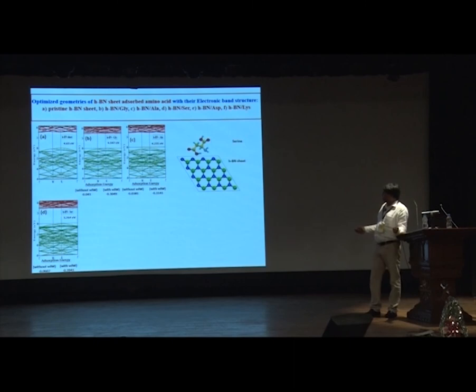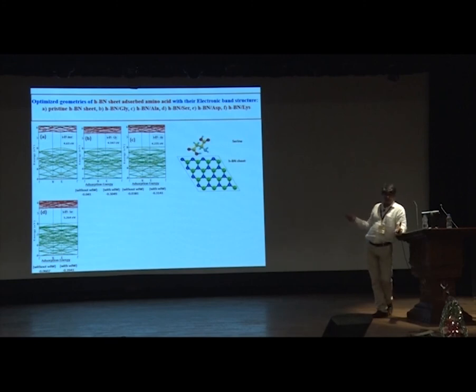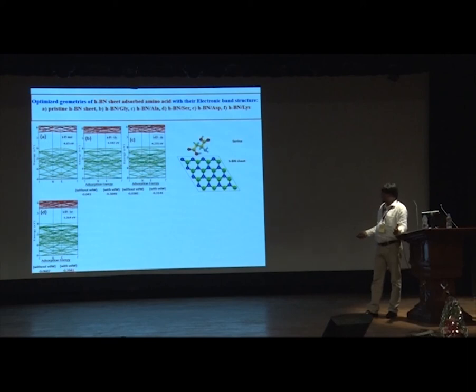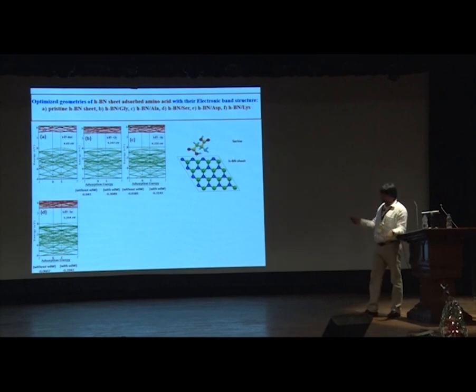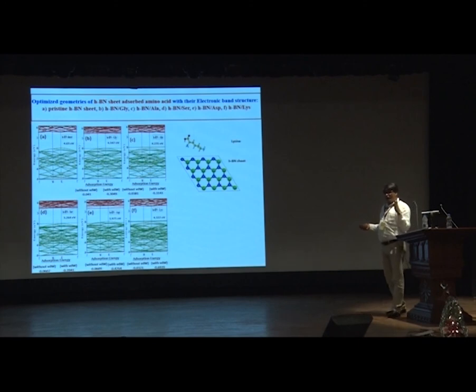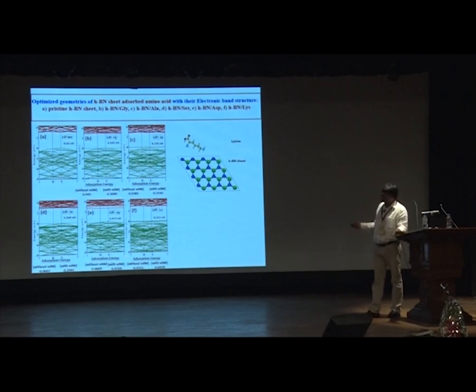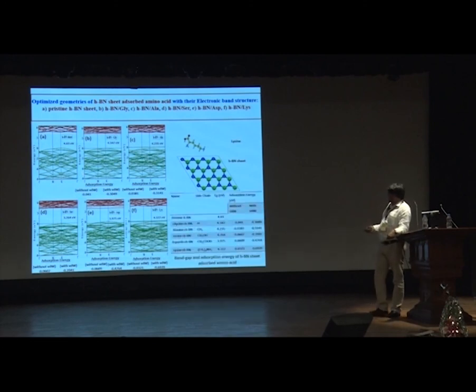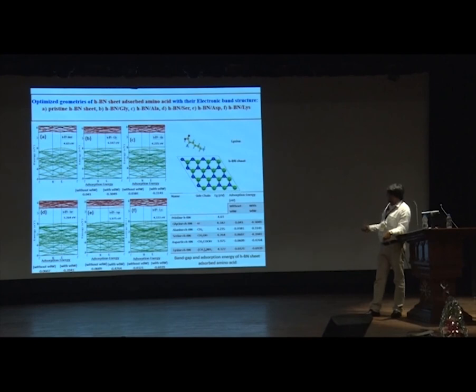For serine, the band gap changes very significantly — it reaches 3.264 eV — demonstrating that by using these biomolecules you can tune the band gap of the system. In this case, the van der Waals contribution to adsorption energy is again significant. For aspartic acid and lysine, similar trends are observed: inclusion of van der Waals interaction significantly increases the adsorption energy, while the band gap does not change as much except for serine.